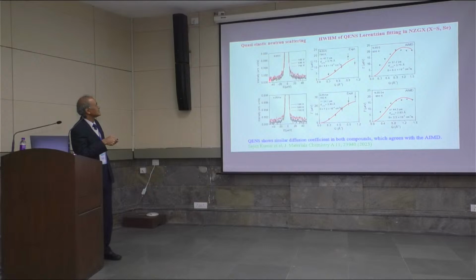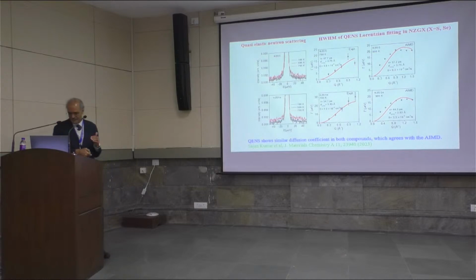And okay, the other kind of measurements, the quasi-elastic neutron scattering, we do see the broadening as a function of temperature. And then this again, the broadening of the elastic line as a function of momentum transfer is plotted. This is experimental data from the Oak Ridge National Laboratory. And we can also have corresponding calculations from the ab initio molecular dynamics simulation. Okay, so this essentially helps in validating the simulations, and then we use simulations for more detailed understanding of the underlying microscopic physics.